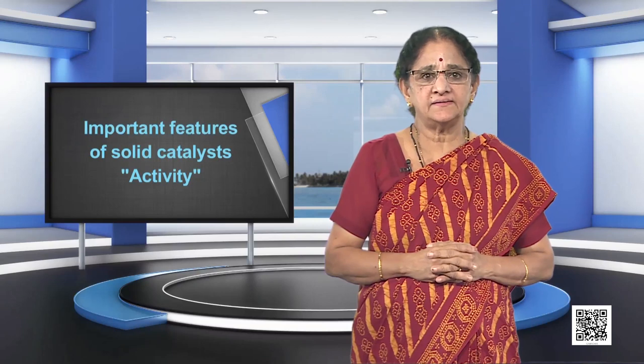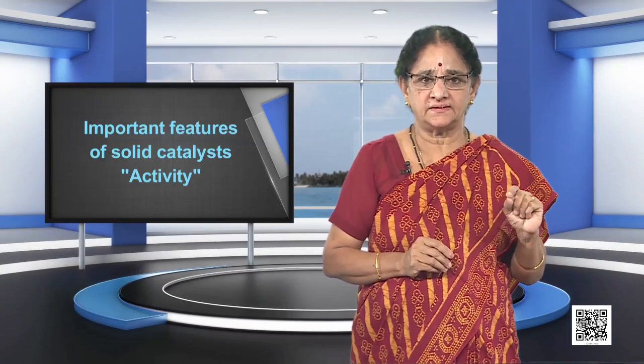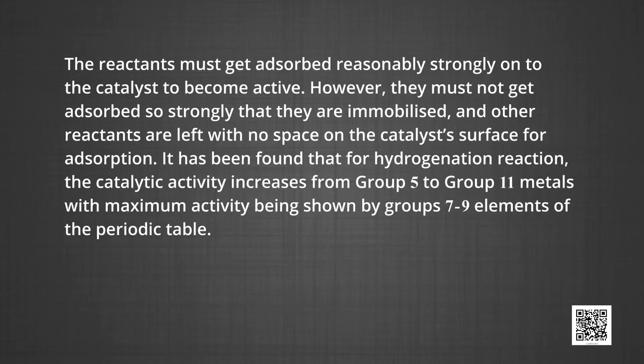Let us consider the important features of solid catalysts. The first and foremost feature is activity. The activity of a catalyst depends upon the strength of chemisorption to a large extent. The reactants must get adsorbed reasonably strongly onto the catalyst to become active; however, they must not get adsorbed so strongly that they are immobilized and other reactants are left with no space on the catalyst surface. It has been found that for hydrogenation reactions, catalytic activity increases from group 5 to group 11 metals, with maximum activity shown by groups 7 to 9 elements of the periodic table.